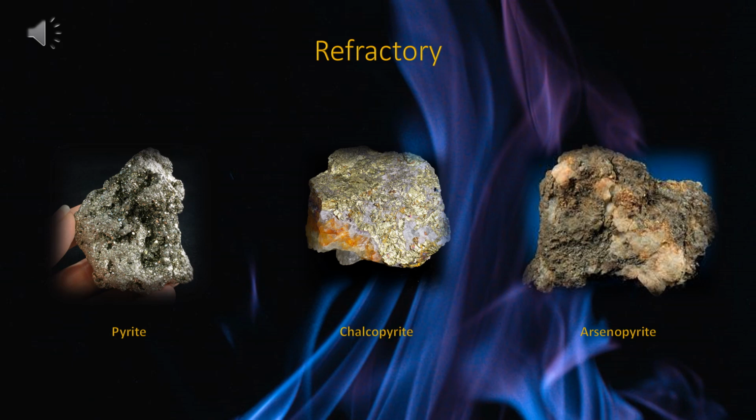Gold concentration can be as high as a couple hundred parts per million for pyrite and chalcopyrite, but it has been reported that concentrations of gold in arsenopyrites have been as high as 10,000 parts per million and more. To a processing plant, these concentrates can be profitable and will purchase this material based on concentration per metric ton.